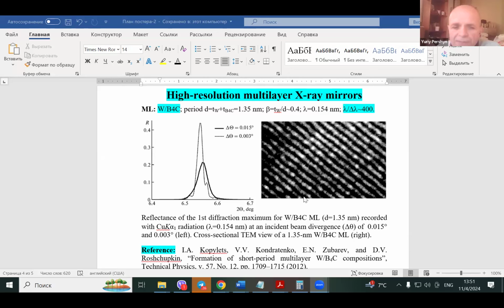So we fabricated tungsten boron carbide multilayer with period, which is the thickness of 2 layers, tungsten and boron carbide, around 1.3 nanometers. Reflectivity, which we have for copper K alpha radiation, is more than 30%, and resolution around 400. The right figure is cross-sectional view in transmission electron microscopy of this sample.